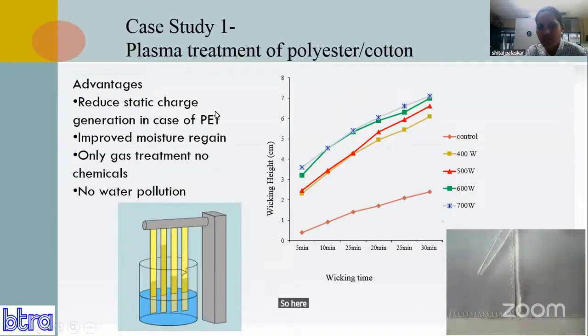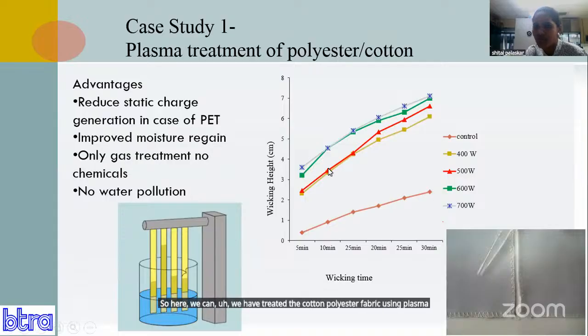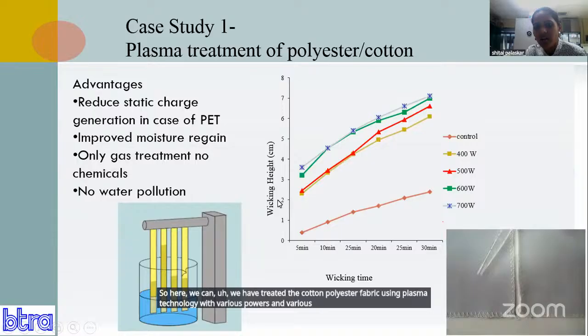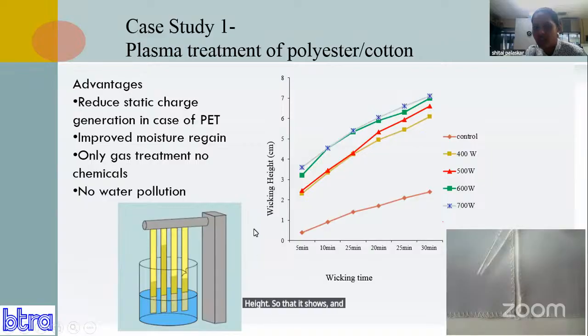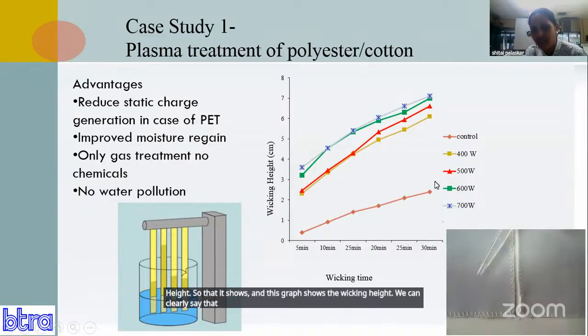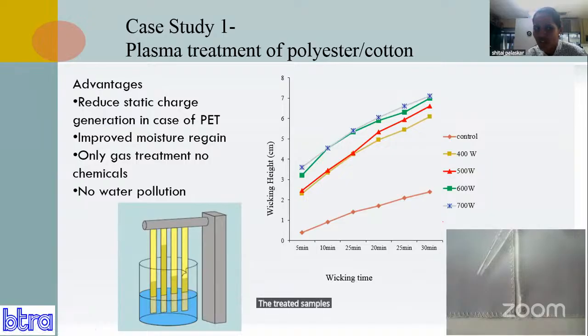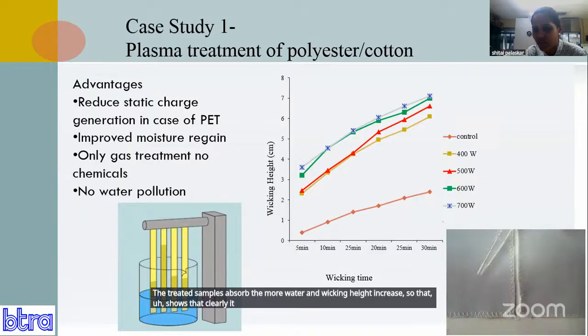Here we have treated the cotton polyester fabric using plasma technology with various powers and various treatment durations, and then the water absorption was checked with wicking height measurement. With respect to time, how high the water can climb is shown, and this graph shows the wicking height. We can clearly see that after plasma treatment, the treated samples absorb more water and the wicking height increases. That shows clearly that the fiber becomes hydrophilic.